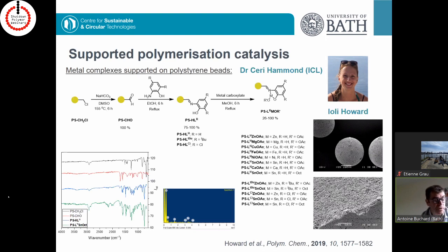And heterogeneous catalysis has been a great way and has been explored in a variety of organic chemistry reactions. In the field of ring-opening polymerization, and for lactide in particular, this has been clearly underexploited. And we thought that there could be some things that we can do in the area. So the first thing we did was ask what type of support we would want for this type of industrially relevant ring-opening polymerization of lactide. And we thought about Merrifield resin and polystyrene beads, and we thought that could be a good starting point to try to build a complex coordination chemistry backbone for our catalyst.